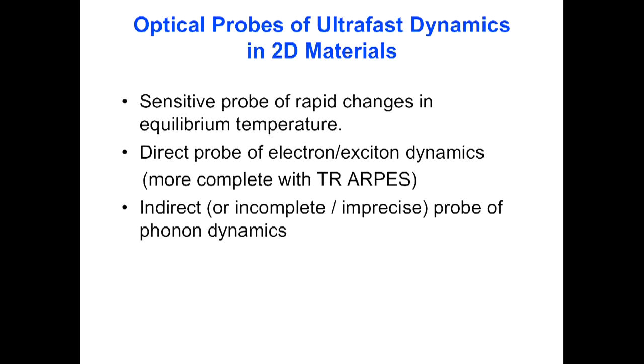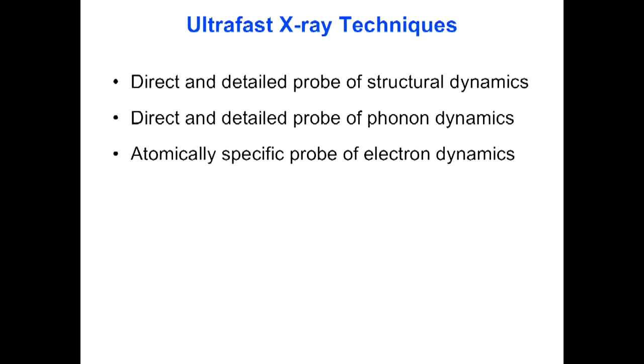But on the other hand, if you want to probe the phonons, it's pretty indirect. You get signatures of the phonons in the electronic structure, and I've illustrated that briefly, but it's pretty incomplete and imprecise. You don't really know exactly what phonons you're looking at. So you don't really have any kind of direct handle on the structural dynamics. So you may infer from this that these are great techniques and you can learn a lot, but there's a great opportunity to make use of X-ray techniques. And what are some of the things that X-ray techniques can provide in this context? Well, you get a direct and detailed probe of the structural dynamics. If you look at that as a quasi-static change, you can look at how phase transitions occur and so forth. Or on a shorter time scale, that same sensitivity gives you a probe of the details of the phonon dynamics.